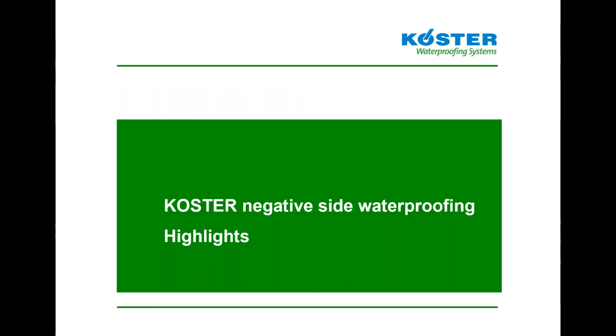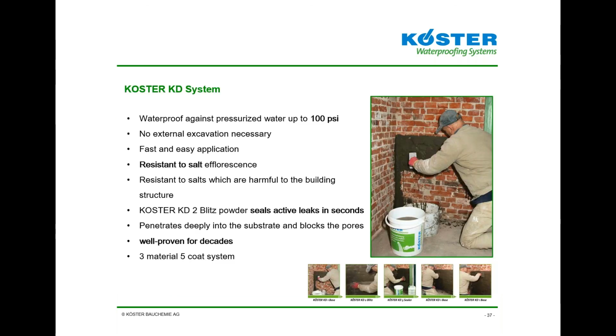Again, going over the 2 different products themselves. KD system, we have that high resistance to pressurized water up to 100 psi, fast, easy application, very resistant to salt efflorescence. Again, this is more for application in brick and masonry substrates that have really been broken down by salt growth and constant exposure to moisture, and have really failed due to exposure to salts, because this does provide a great protection against salt efflorescence and crystal growth or anything like that.